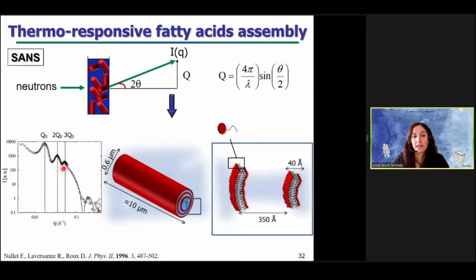These peaks show that lamellar phases are present in solution. That is to say that the tubes are not empty tubes, but they are multilamellar tubes, as drawn here. So they are micron-sized multilamellar tubes. From the position of the peaks, you can determine the interlayer spacing between two bilayers inside the tubes. And from the information on the large wave vector part, you can determine the bilayer thickness of the bilayer inside your tube.